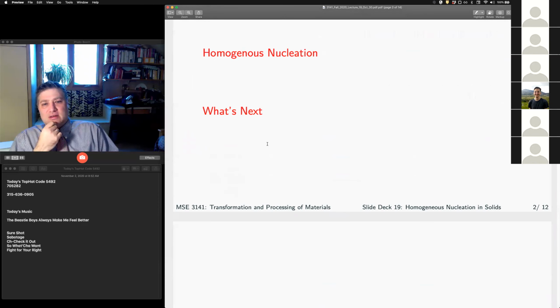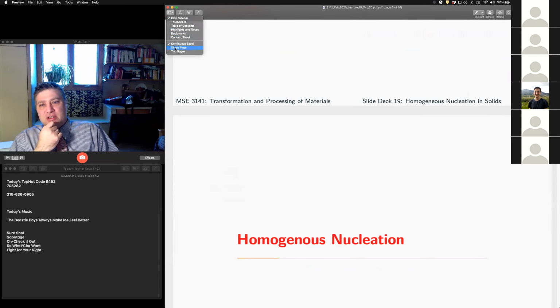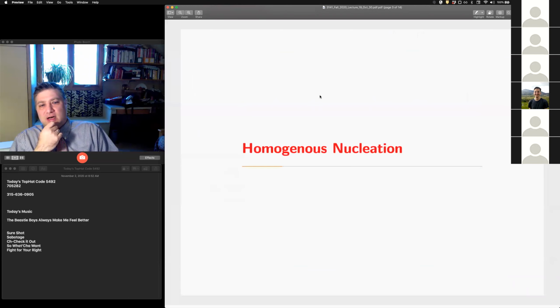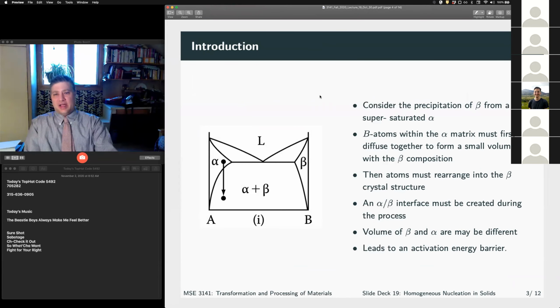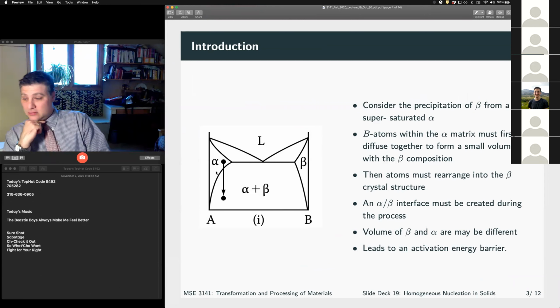Okay, so let's hop into this with homogeneous nucleation in the last bit of time. If we think about precipitation, I go from alpha, we're holding at this temperature. Let's just pretend we hold at this temperature for a long enough time that everything becomes nice and homogeneous. And then we rapidly quench it down. Now we're at this temperature, and I have a very significant undercooling from the equilibrium transformation temperature from alpha to beta.